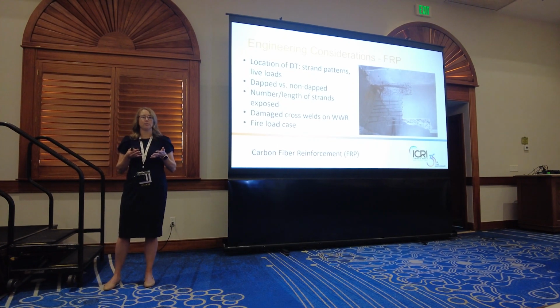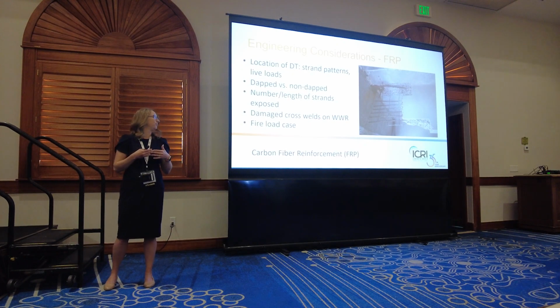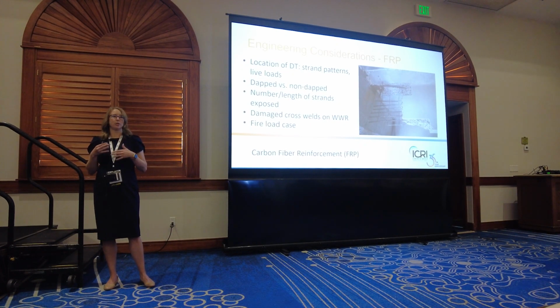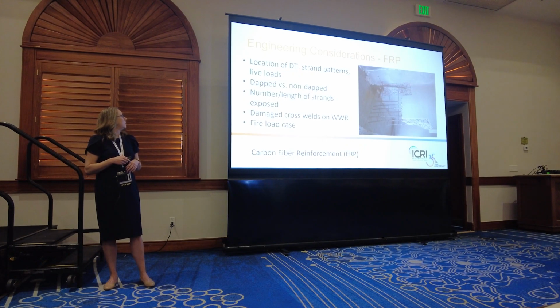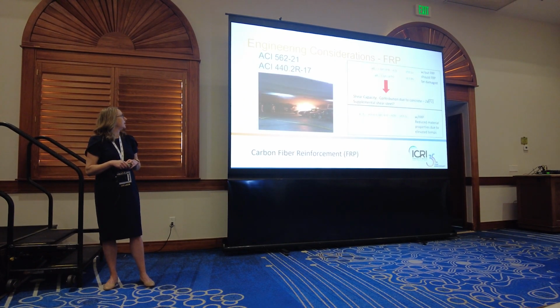When you see welded wire reinforcing within a double T-stem, it's important to note that this is structural. Sometimes that's thought of as non-structural reinforcing, but when you're in a double T-stem, we engineers are counting on that for our shear capacity. So you always want to try and chip as delicately as possible, and really we're trying to maintain the cross wires because that's what provides us with the development length that we need. And then finally up here we have the fire load case.